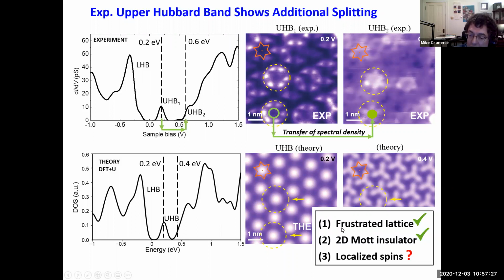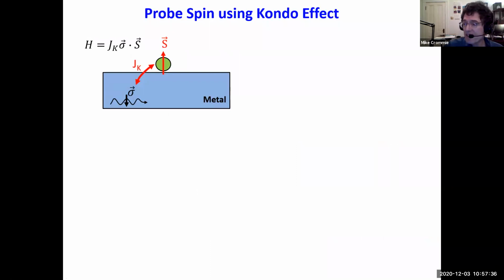But that means that we have 2 out of 3 of these criteria satisfied by our material. But what about the local spins? Do we have spins? Well, to answer that question, we decided to use the Kondo effect to see if we could detect spin behavior in our system. And so I'll just remind you what the Kondo effect is. The Kondo effect is what you get when you have a local moment in contact with a metal, in which case the spin of the local moment interacts with the spin of the itinerant